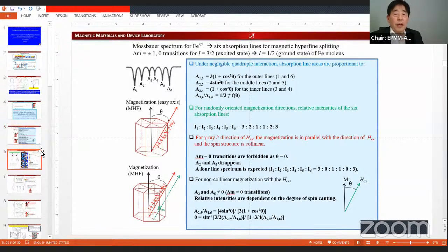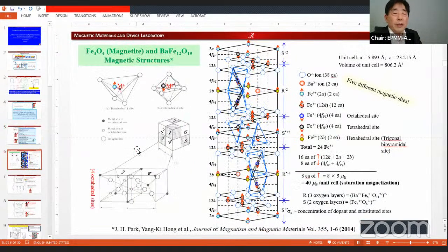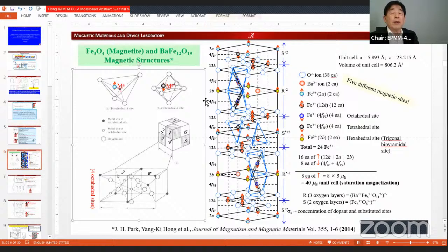Next one, let us take, for example, M-type hexaferrite. M-type hexaferrite has 5 different magnetic sites. Each individual site induces a 6-peak spectrum, and 6 peaks times 5 sites means 30 peaks will appear from hexagonal barium ferrite, with a formula like this here. So we will analyze the 30 peaks out of the Mössbauer spectrum to understand isomer shift, hyperfine field, and quadrupole splitting. Finally, we will predict the magnetic crystalline anisotropy constant and the saturation magnetic moment.